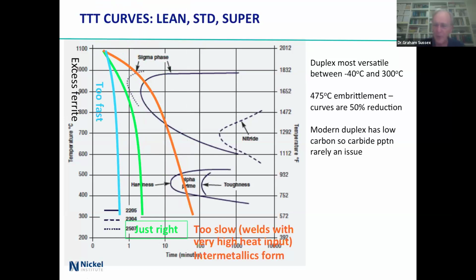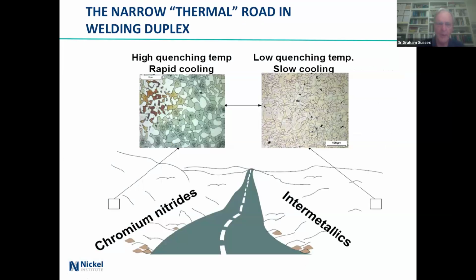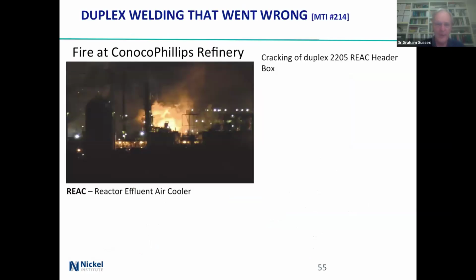And I've said before, modern duplex, low carbon, so carbide precipitate is not usually a problem. This is the thermal road. Chromium nitrides on one side, intermetallics on the other, high ferrite on the left, high austenite on the right. And you wind up with that sort of microstructure. And the black dots in the high austenite side are intermetallics. There aren't a lot of them there, that probably would pass, but it's not good.